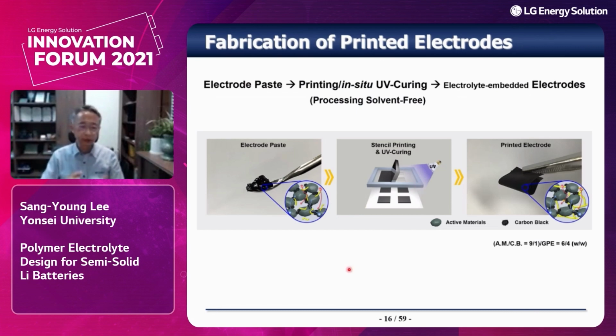Here is the fabrication procedure. Similar to what I discussed previously, we started with the electrode paste, which contains the electroactive materials, carbon blacks, and our electrolyte precursors. The paste was subjected to printing, followed by in situ UV curing. Eventually we have obtained the electrolyte-embedded electrode like this. To make conventional liquid electrolyte-based electrodes, we should rely on solvent processing, such as NMP or others. In that case, we should be careful about how to remove the processing solvent. By comparison, in our case, we did not use any processing solvent. Just printing followed by UV curing. That's all. So we can fabricate an electrolyte-embedded solid-state electrode.